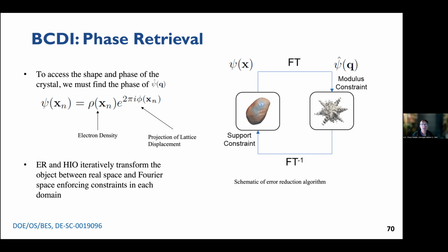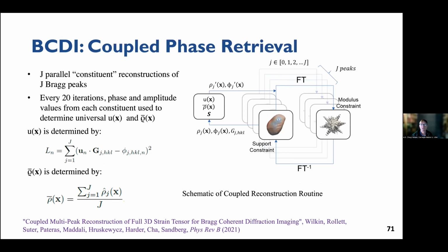The main things that we've been working on in recent times, obviously this originally started with getting an individual peak and reconstructing an individual grain. The limitation of that is it gives you information only along the diffraction vector. And if you want the full displacement field, as we surely do if we want to go hunting for dislocations, you need at least 3 independent peaks so that you've got a basis set, if you like, for recovering that.